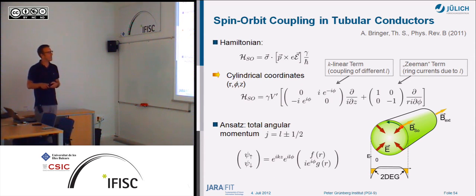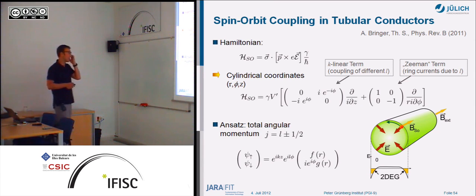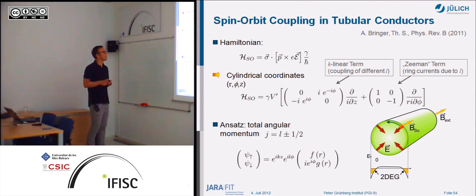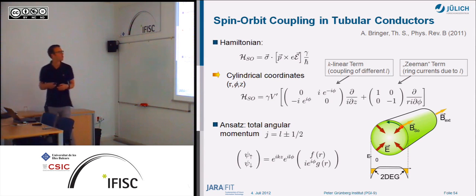So the system is like this. We have a nanowire here, an indium arsenide nanowire, with a surface electron gas. We have some internal electric field, which gives you some spin-orbit field here. And we apply an external magnetic field along the wire axis here. Yeah? And you do the same as you did before for a two-dimensional electron gas. You have your spin-orbit coupling term, which involves the momentum here, the electric field, and the spin here. So the faster the electrons are, the stronger the spin-orbit coupling is.